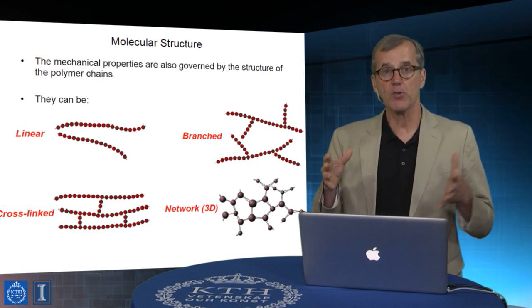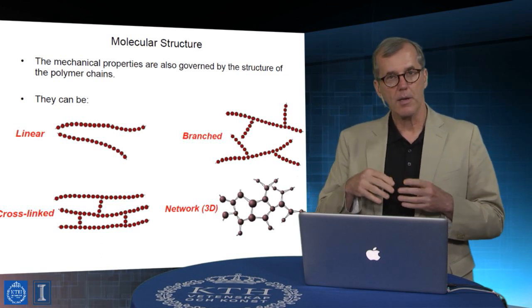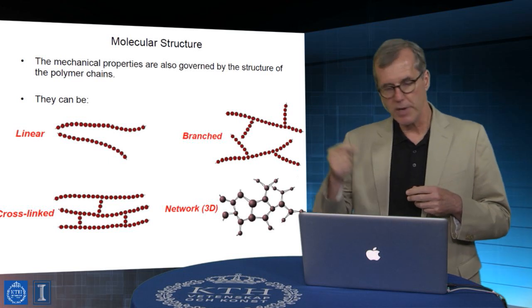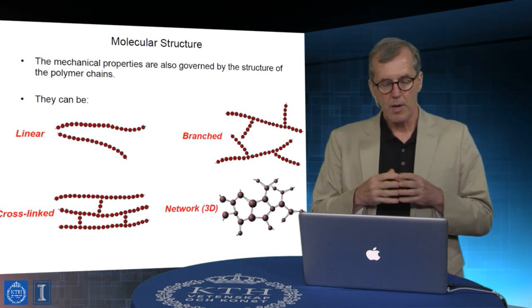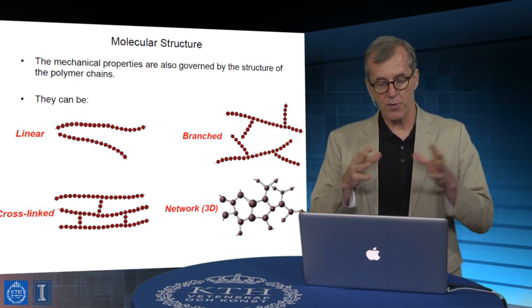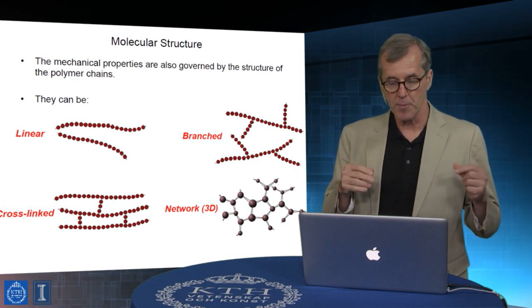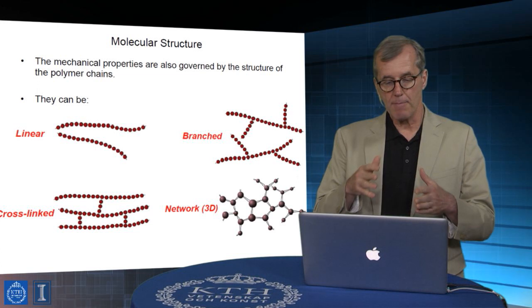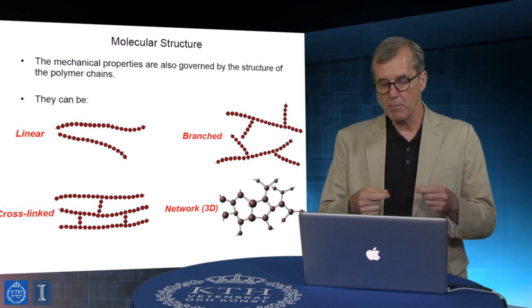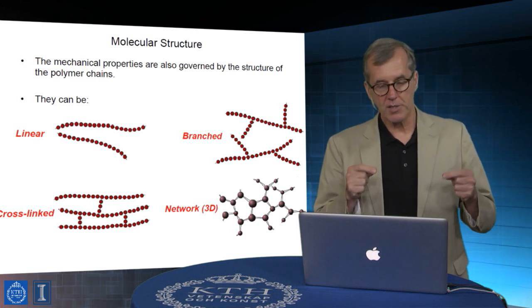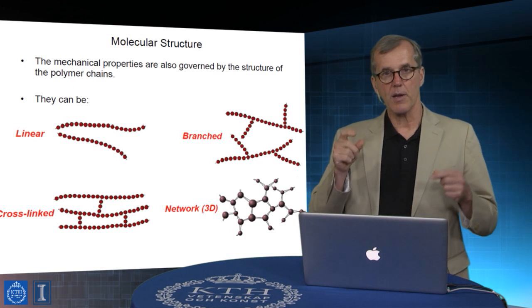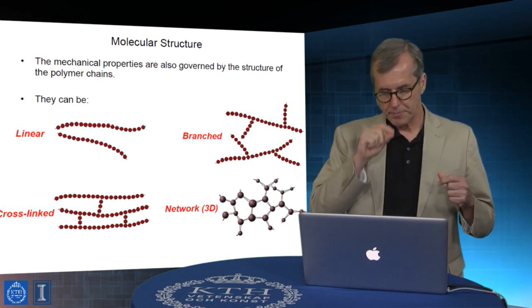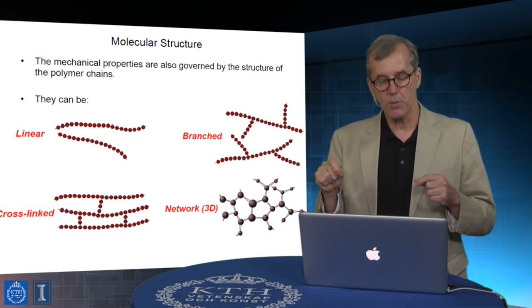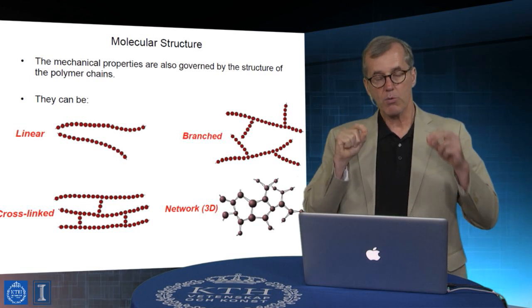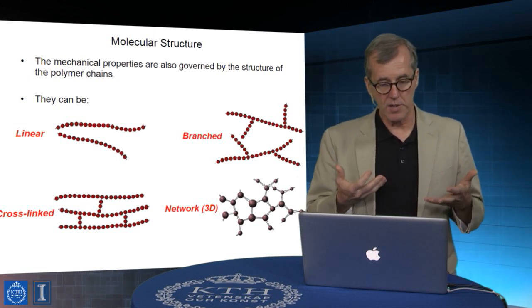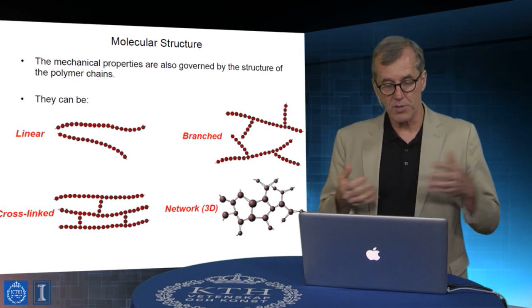There are things that would be happening in the chemistry to make that happen, and that's understood, for example, by chain transfer mechanisms and a variety of other things. Molecules can be cross-linked. So, for example, if they're sparse, we might generate gel phases that way. But you can see that when we break down the topology from this linear sequence to something that's a little bit more two-dimensional, these are objects that, at any degree of conversion, if I put together n monomers in a linear sequence, and I put together n monomers with cross-links, you get higher molecular weights when you have cross-link structures present.